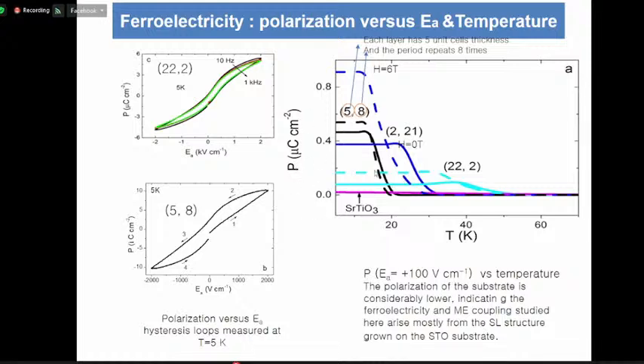Then this polarization depends on the period. It's the 2 unit cell thickness, 22 unit cell thickness, and then 5 unit cell thickness. This means 5 unit cell thickness of each layer and 8 times repetition. This case is 2 unit cell thickness of each layer and 21 times repetition. Depending on the period, the polarization shows differently. The transition temperature is 20 Kelvin, sometimes 40 Kelvin like this. In the case of 5 unit cell thickness, it is a 20 Kelvin transition temperature, and the 22 case is around 40 Kelvin transition temperature.